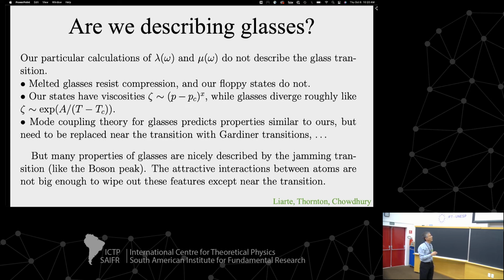More specifically, like mode coupling, we have a viscosity that grows as a power law. Real glasses, there are immense numbers of experiments and controversies, but they basically follow something like a Vogel-Fulcher law, which grows exponentially as you approach a temperature which is well below what we would call the glass transition temperature, but that's where it freezes out of equilibrium. It's sometimes called the Kauzmann temperature, but whatever, it looks like this, which is much different from a power law. It grows much more severely. And I already apologized for complaining about mode coupling theory for all those years.